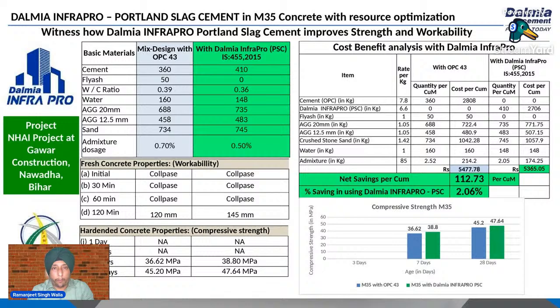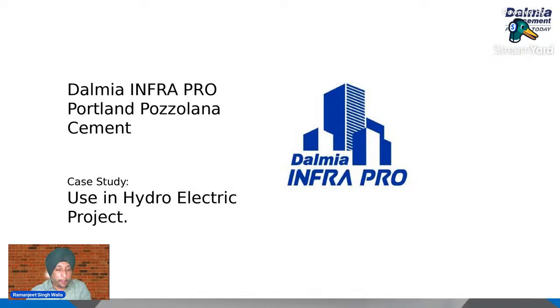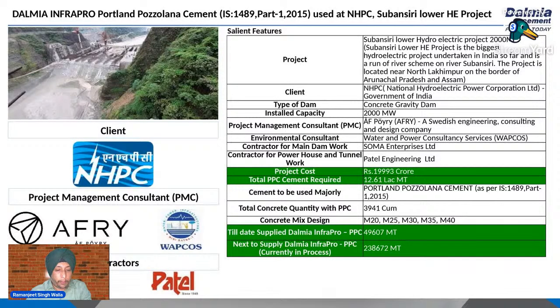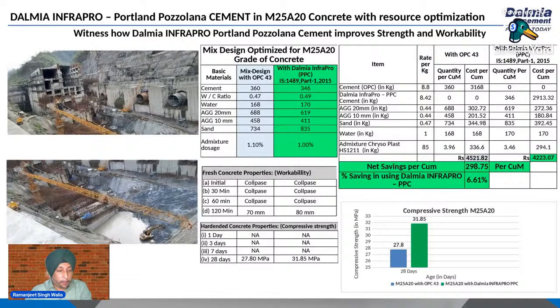Now they have started trials with composite cement also. They are getting good results, and the workability is better with the blended cement as compared to the site blend. We use 0.5% admixture and we are getting 145 slump in 2 hours, whereas with OPC plus fly ash blend they were getting 120 slump, and the mix was also harsh. This is hydroelectric power. Here also we are using our PPC successfully in M20, 25, 30, 35, 40, all, because here the heat of hydration is a big problem. So they are using PPC only, in mass concreting works.